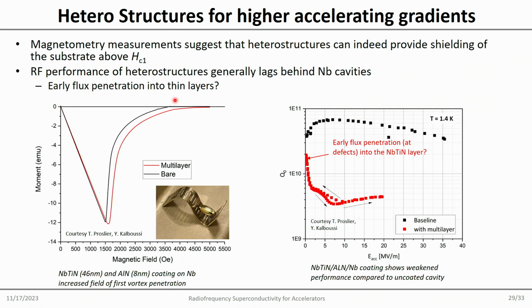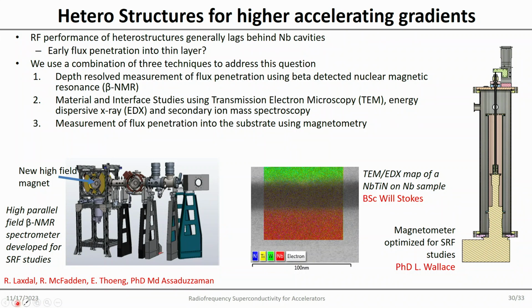So what do we want to do? We have 3 experiments that we want to combine to get a full picture. The first one, I told you in the beginning about, is beta-NMR, beta-detected nuclear magnetic resonance. This is a depth-resolved technique, and you can use NMR techniques to get magnetic fields, somewhat indirectly. We have this specifically built spectrometer which can go up to the fields we are interested in and can measure magnetic flux penetration on a nanometer scale. At this field level, this is the only facility worldwide which can do that.